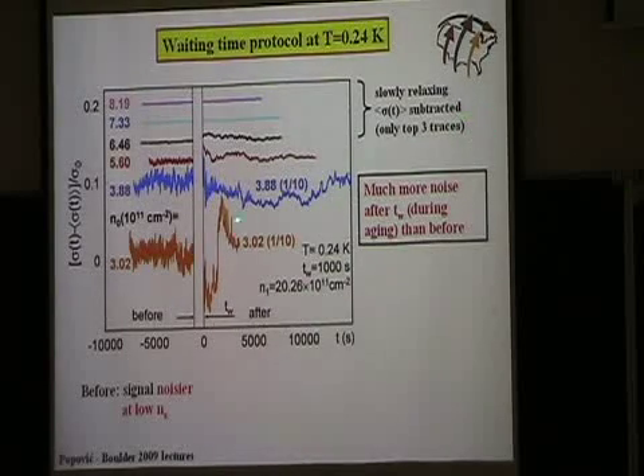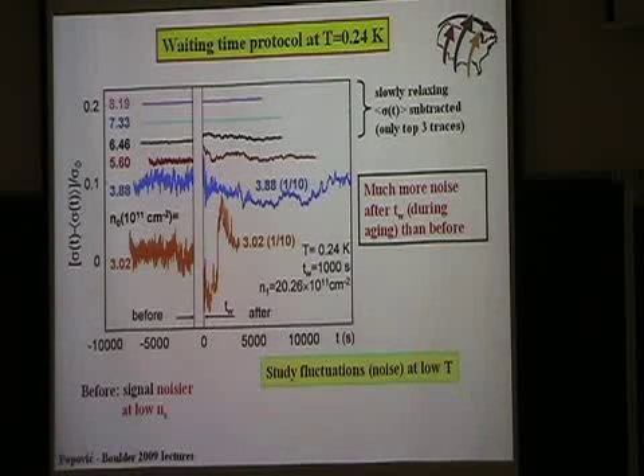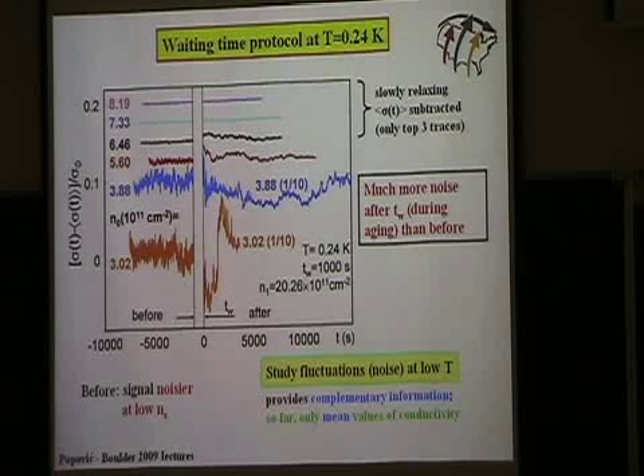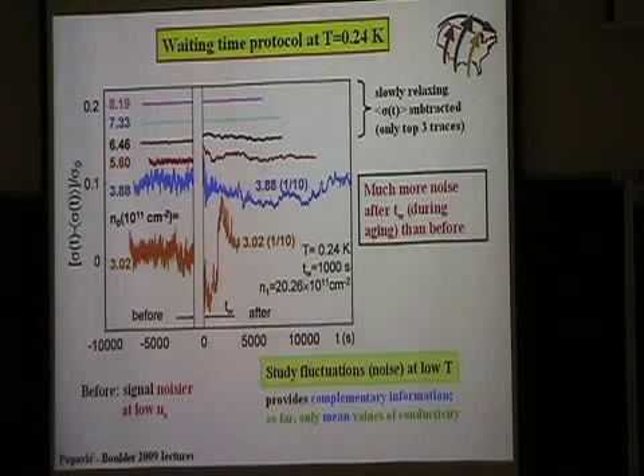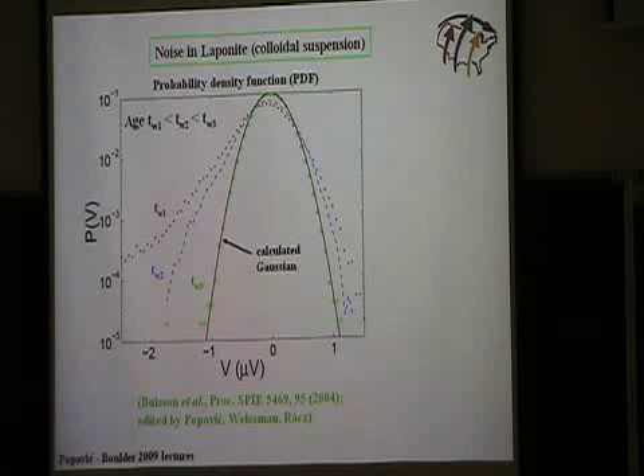You can also see that here there are no visible relaxations, so it is impossible actually at low temperatures to study the relaxations because the signal is so noisy. So you're kind of stuck with these fluctuations, and if you want to learn something, you have to study the fluctuations. You cannot study the relaxations. So this is what we did at lowest temperatures, and of course this is going to provide us with some complementary information because the measurement of the resistivity is just really the average, the mean value.